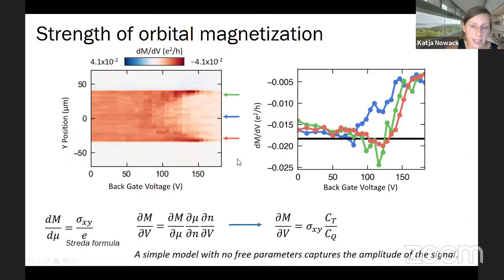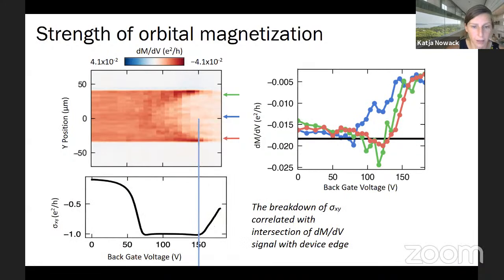And so this is this black line, and then the colored lines are actually just horizontal traces at 3 locations of this data. And so we get quite good quantitative agreement between the signal size as we are fully tuned into the valence band and what we actually measure. So that's nice. And then we can also say that the decrease in signal that we observe here really coincides with sigma xy starting to strongly deviate from the quantized value in the device.